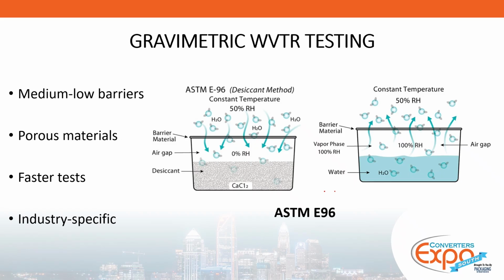So ASTM E96. This is a good method up until, I would say, 8 to 10,000 grams per meter square per day. Then that's where this still air gap comes in, that you can see in the diagrams here. So you have your dry and your wet cup, and then you have a gap, and then you have your barrier sealed to the top of the cup. Once you place these in a humidified environment, you're either going to get moisture moving into the cup or out of the cup, depending on if you're using a desiccant or the water method.